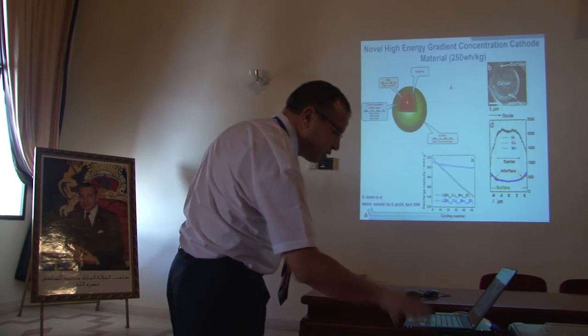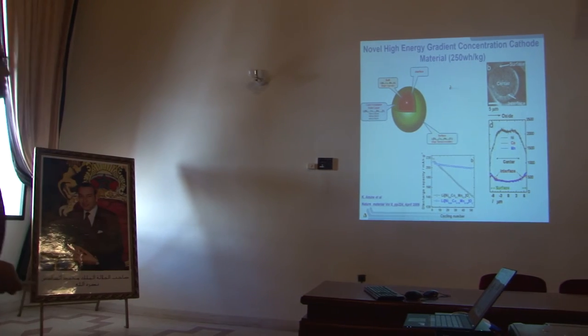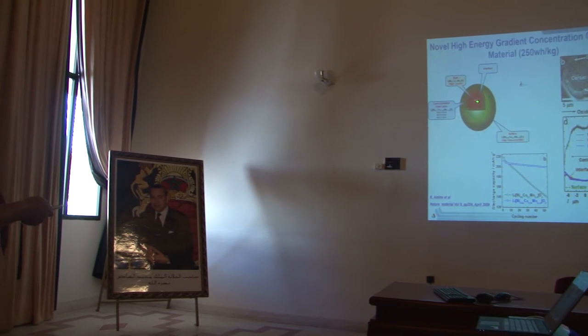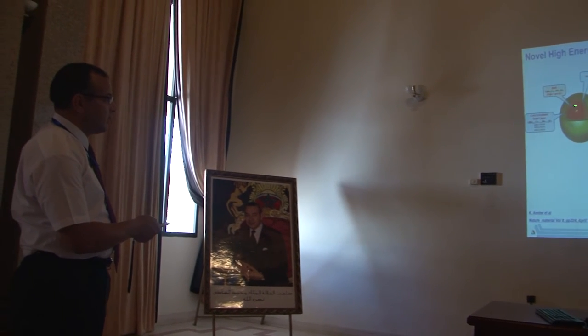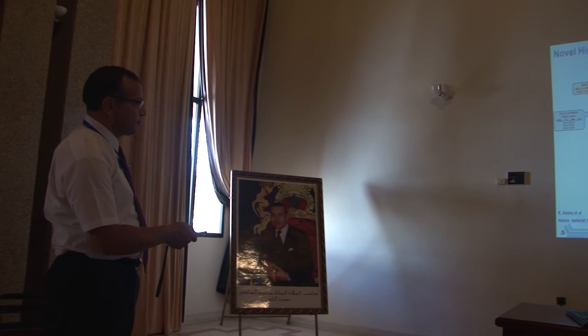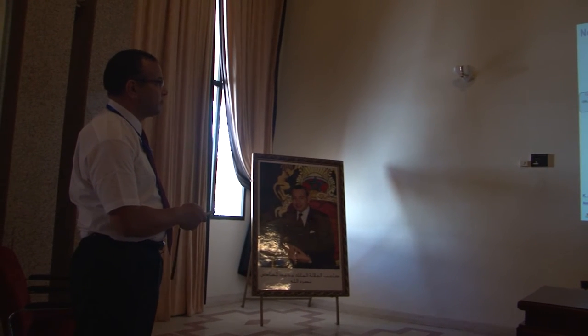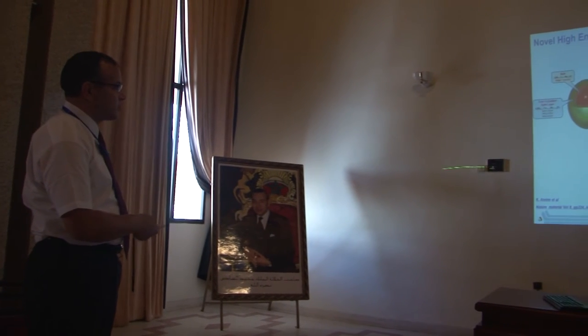And that leads us to the first concept, which is a core shell with gradient. So basically what you do, you have a nickel-rich core here to give us capacity. At this point, you start reducing the nickel and increasing the manganese, see? And cobalt if you want. So you end up with a core shell with gradient. And you can see by making this material, you get much better stability at high voltage and high capacities.